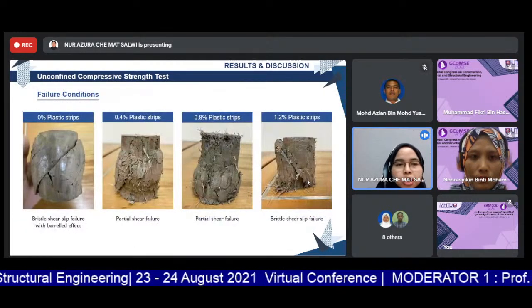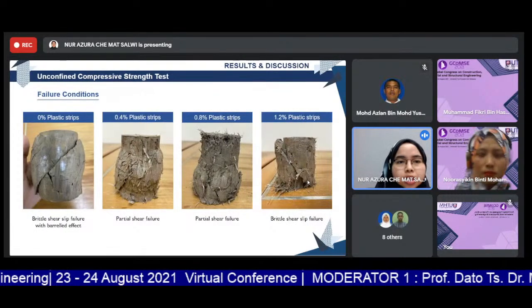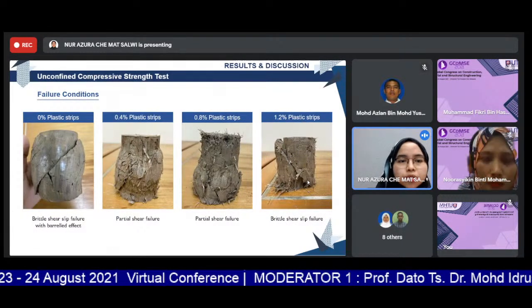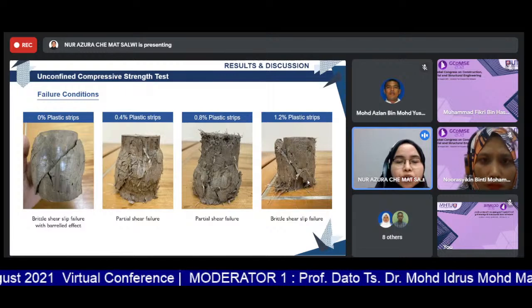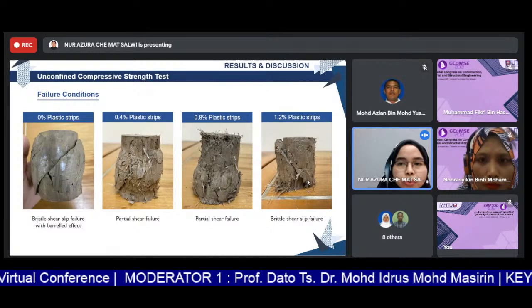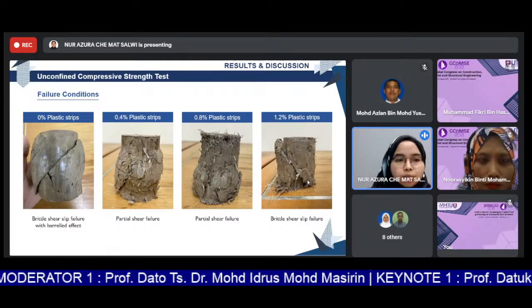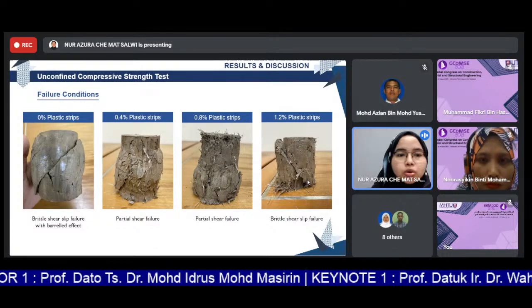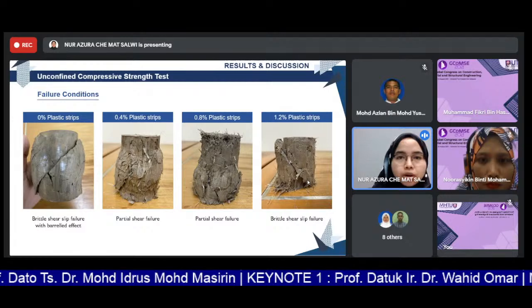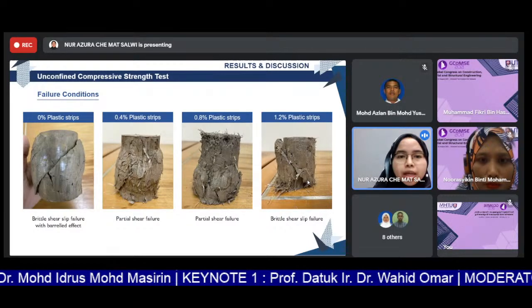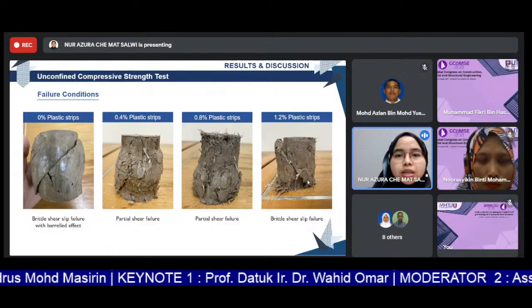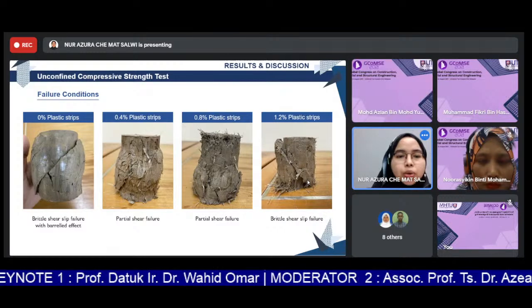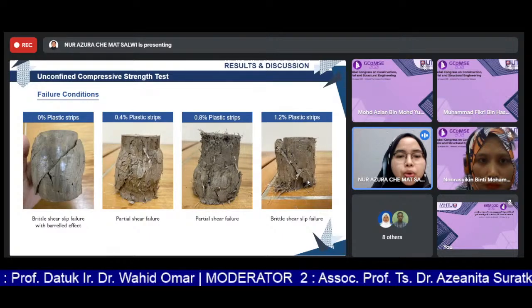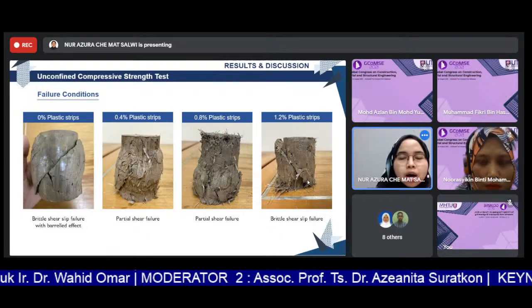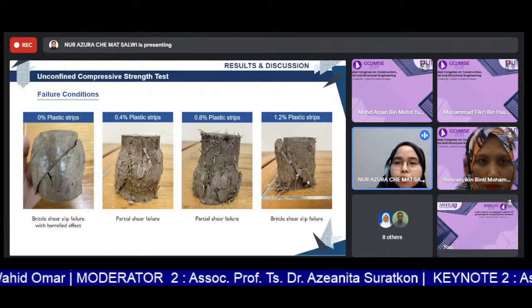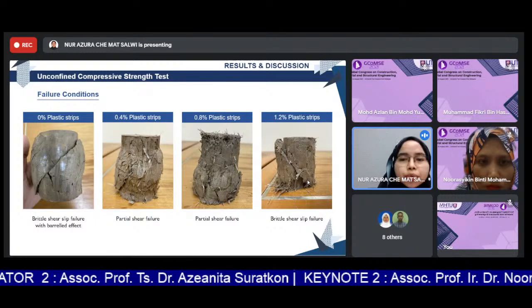As we can see from here, these are the failure conditions of the soil specimen after reinforced with 0, 0.4, 0.8, and 1.2% of plastic strips. Initially, without any insertion of plastic strips, the soil specimen undergoes brittle shear slip failure with barrel effect. But then after insertion of 0.4, then 0.8% of plastic strips, the soil specimen undergoes partial shear failure where minimal shear appeared. But then after insertion of 1.2% of plastic strips, the soil specimen again undergoes brittle shear slip failure.